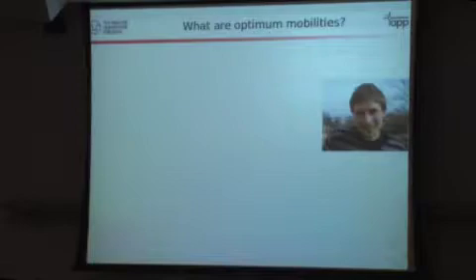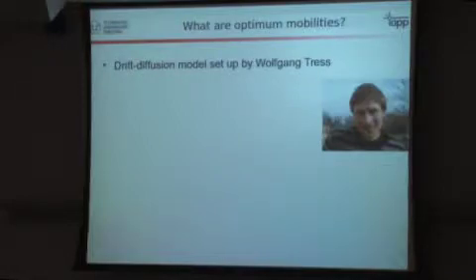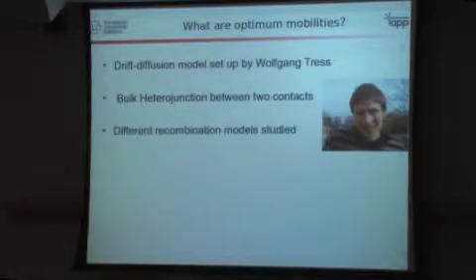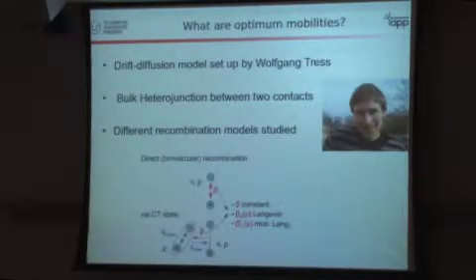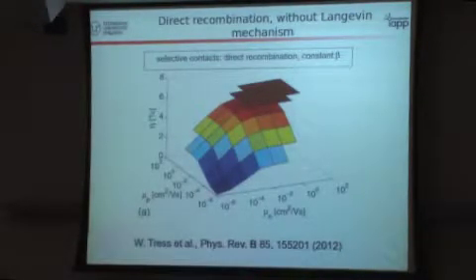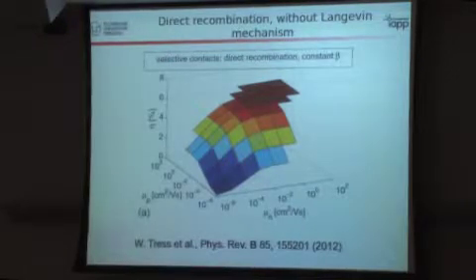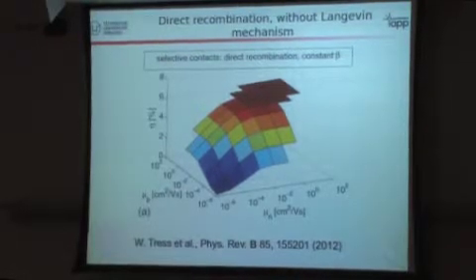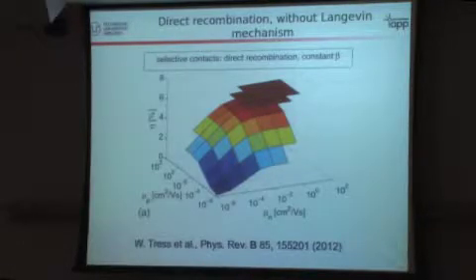Now, back to this mobility question, these are some calculations Wolfgang Tress did in his PhD thesis. He made a drift diffusion model and calculated a simple bulk heterojunction device, and he used different recombination models: a very simple direct bimolecular recombination model, and a somewhat more involved Langevin model, which is probably more appropriate for organics, where the diffusion of the carriers is also important. When he uses the simple recombination model, it turns out that the efficiency of the device as a function of mobilities for electrons and holes increases and reaches a plateau at about 10 to the minus 3. So then you are not limited by mobilities anymore. So the basic conclusion would be you have to have 10 to the minus 3 or better in mobilities.